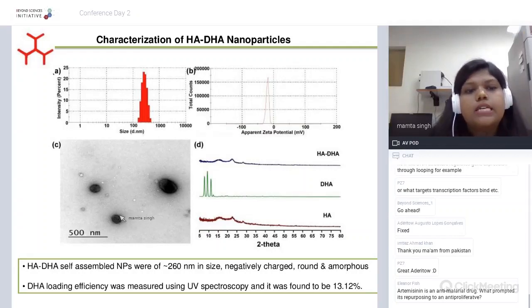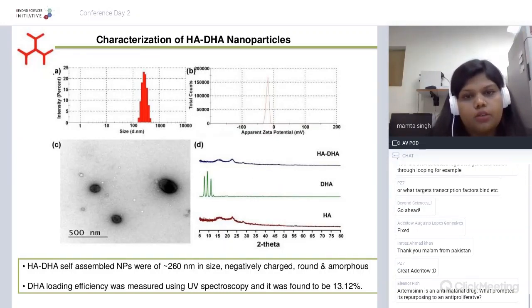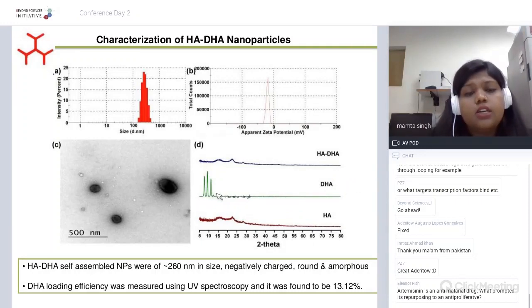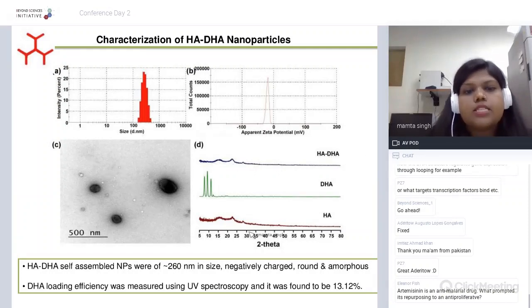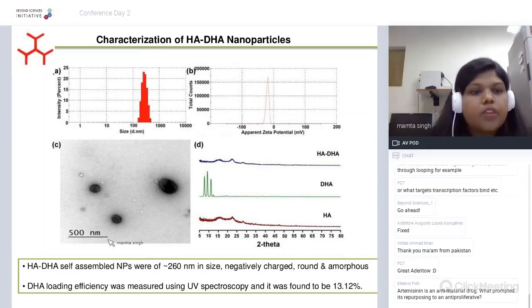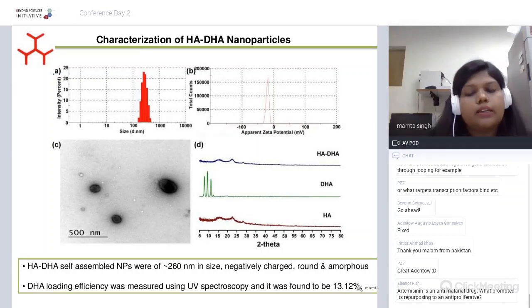Surface morphology analyzed by transmission electron microscopy showed circular particles with no aggregates. X-ray diffraction analysis revealed that pure DHA shows a crystalline nature with three signature peaks, whereas HA and the final product showed an amorphous nature. This amorphous character in therapeutic agents helps with better dissolution, absorption, and bioavailability — solving the solubility issues currently present for these drugs. Drug loading efficiency was checked using UV spectroscopy and was found to be higher than previously reported pegylated conjugates.